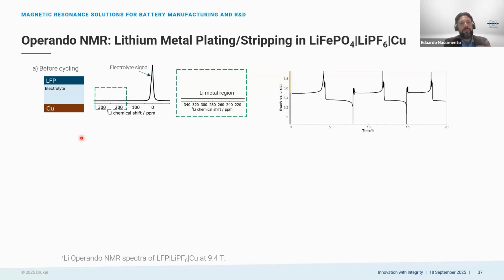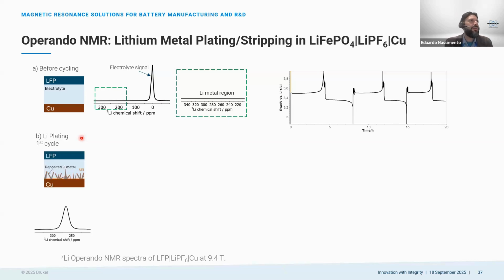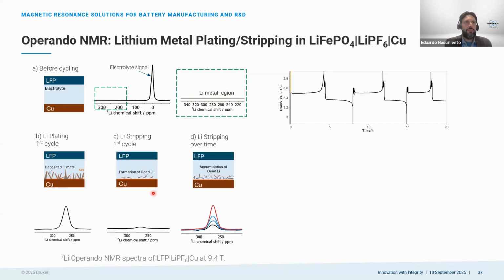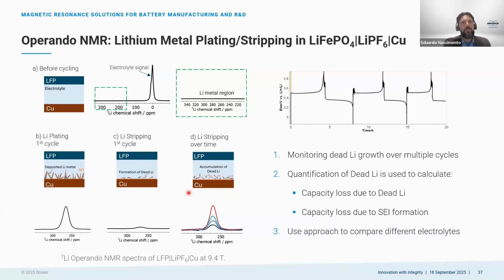And then we applied some cycling, some charging to this battery. After some time, you are going to see the lithium metal being deposited here in the collector, but also in the SEI phase. And then after some time, you see the formation of dead lithium and, over time, the accumulation of dead lithium in your battery cell. Monitoring dead Li growth, you can calculate the capacity loss due to dead Li, but also the capacity loss due to the SEI formation. You can use that to compare different electrolytes, for example.